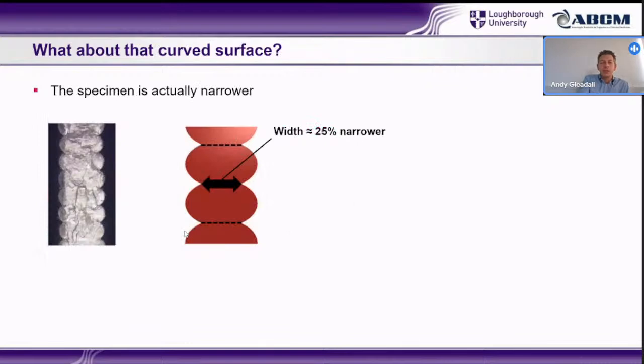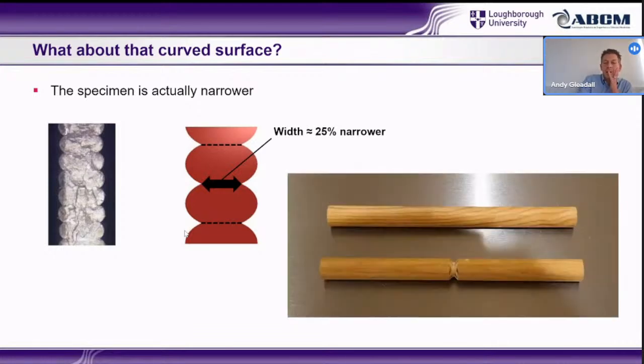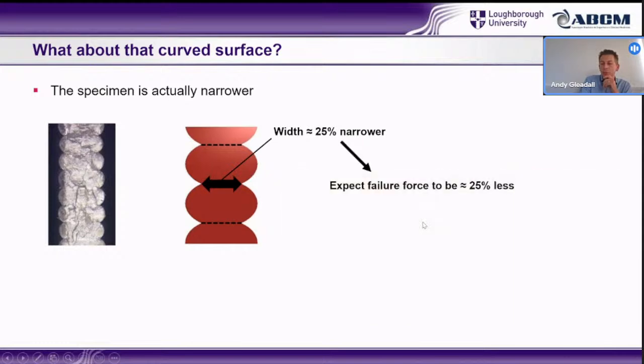But actually, when we looked at it, which we were really able to do easily because it's such a simple specimen, and measure the width, then the width being 25% narrower, it's kind of like gouging out a groove in something. And this one I could snap really easy. This one I couldn't snap easily at all. And that's basically what we're doing. We'd expect the force to be less, and it actually is.